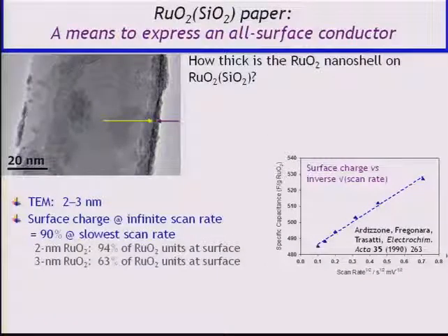all surface. And if you do some calculations based on the unit cell of rutile, a 3 nanometer bit of rutile would have 63% of the units at the surface, 2 nanometers, 94%. So again, this falls in that sort of 2 to 3 nanometer ballpark.